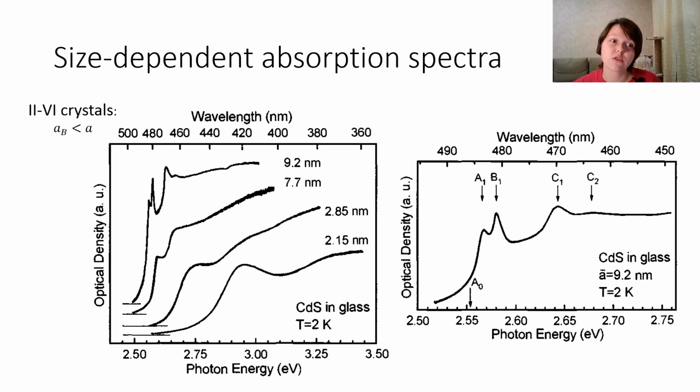What I want to tell you about this type of crystals: II-VI compounds provide evidence for the smooth evolution of the fundamental absorption spectra from crystal-like to cluster-like properties via weak, intermediate, and strong confinement regimes.